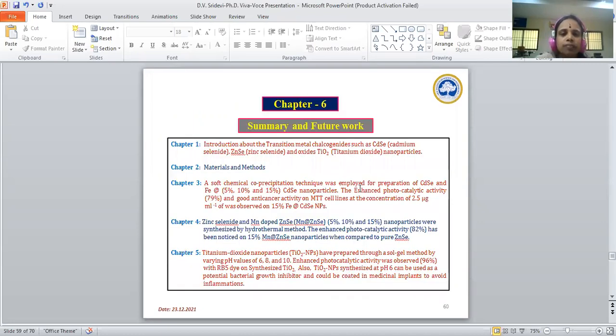Summary and future work. Chapter 1, introduction about the transition metal chalcogenides such as cadmium selenide, zinc selenide, and TiO2 nanoparticles. Chapter 2, materials and methods. Chapter 3, a soft chemical co-precipitation method was employed for the preparation of cadmium selenide and Fe-doped cadmium selenide nanoparticles. An enhanced photocatalytic activity of 79% was observed, and it acts as a good anti-cancer agent on breast cancer cell lines at a minimum dosage, observed with 15% Fe metal doped cadmium selenide nanoparticles.